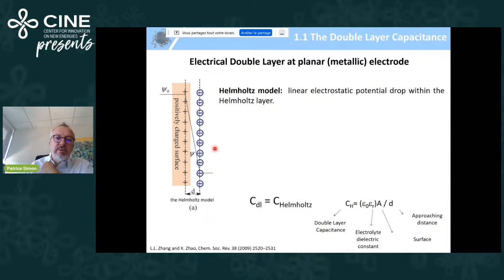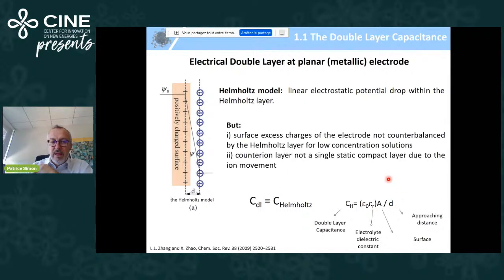So the first model is the Helmholtz model, which states a linear electrostatic potential drop within the Helmholtz layer, which is constituted by the counter-ion adsorption from the electrolyte side to balance the positive charge you inject into the carbon. And the double layer capacitance is the Helmholtz capacitance, the one I just mentioned before. However, you have two drawbacks. First, the surface excess charge that you put in the metallic or conducting electrode may not be counterbalanced by the Helmholtz layer when you use low concentration electrolytes. And the second point is that the counter-ion layer is not static because of the ion movement.